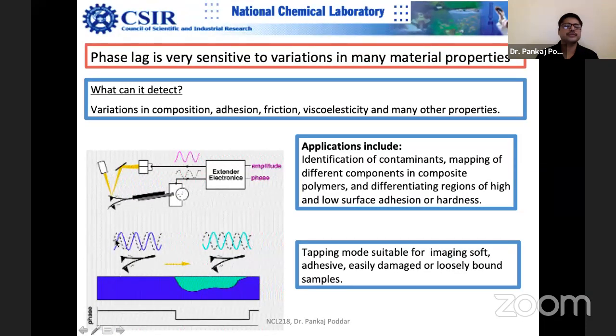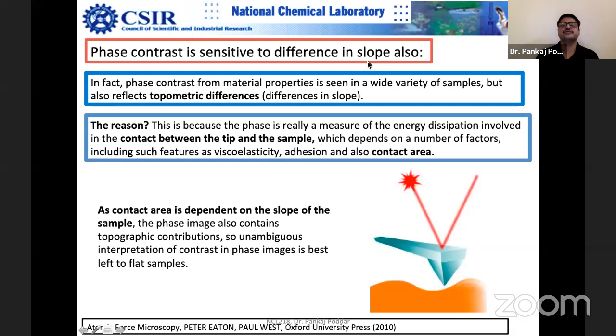You can see there is a small phase change, but when you come to a different surface, you can see that the phase change becomes larger and larger. So that gives you an idea about softness or hardness or adhesiveness of the specimen. And phase contrast is sensitive to difference in the slope as well. So you have to be careful that it should not be the case.